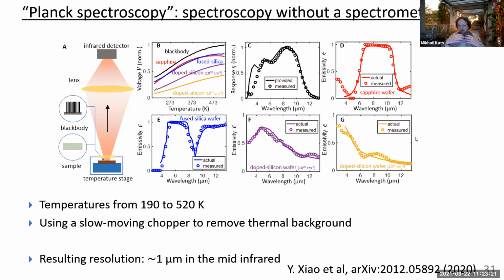And then there's pretty much no way to simultaneously extract a temperature-tunable emissivity and the spectrum of the emissivity at the same time using this kind of approach, just because you don't have enough data to be able to do that inversion. Okay, it's too many degrees of freedom that you're trying to fit. Yeah, that's right. So this is the range we used. You could certainly go higher. You can easily go up to like 800 K for most materials, but this is what we happen to use.